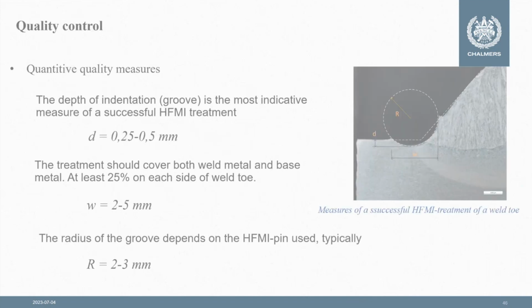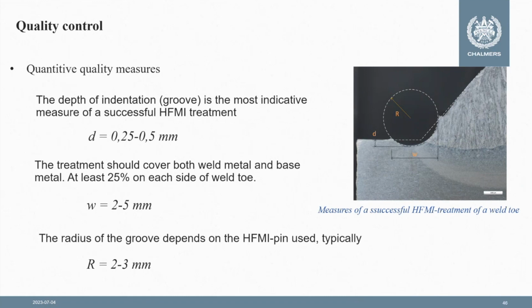I'll skip this one and show this one instead, which is about the quality, qualitative or quantitative measures. Most important is the depth of the groove. This is different depending on the intensity setting of the tool, which is related actually to the steel. So for higher strength steel, this depth D would be a little bit shallower than for S355 or S275, typically in the range of 0.25 to 0.5 millimeters.